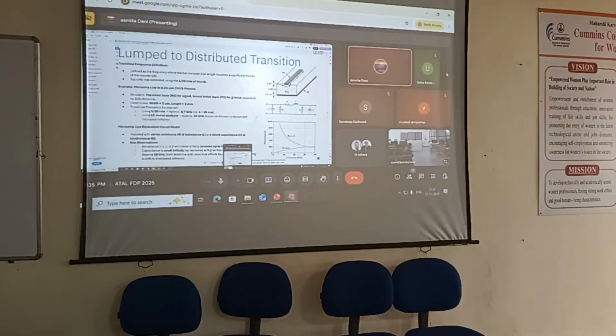behavior. So we see that if we model it with a simple series R, inductance and shunt C and conductance model, the inductance of 1.1 to 1.2 nanohenry of the line remains fairly constant up to 10 gigahertz, and then capacitance is small initially, but it starts increasing at higher frequencies because that gap to ground effect starts becoming very prominent. So that's why the model starts becoming distributed and it no longer acts as an ideal inductor.